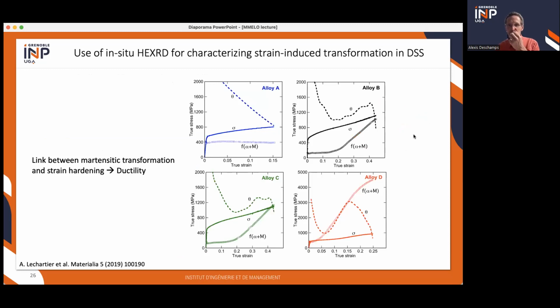And now, if you relate these in situ measurements with the mechanical properties, well, as you expect in the stable alloy where you have no transformation, the austenite is stable, there is no martensite forming, then you have a classical decrease of strain hardening rate with increase of stress. And when you get to the Considère criterion, the two equal, then you have ductile failure.